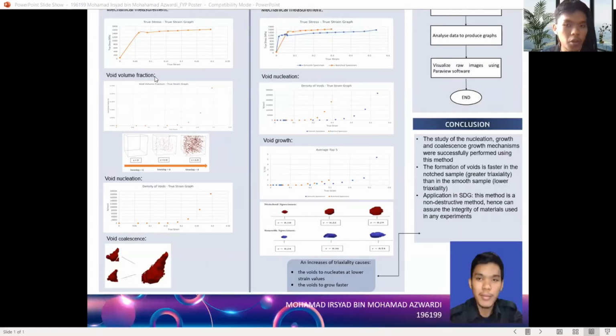Okay, so the second one is the void volume fraction. The void volume fraction shows the volumic amount of damage. As you can see here, the damage seems to increase at an exponential rate at around a strain value of 0.2. The figure in the box also illustrates the qualitative observation, which is a 3D view of the voids formed along the strain. At strain equal to 0, we can see that there are no voids inside the metal. At strain 0.18, a few voids have appeared, and at the highest strain of 0.29, there is a lot of nucleation of voids inside the metal.